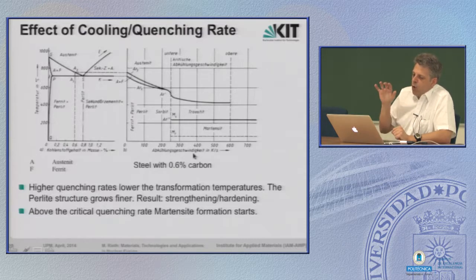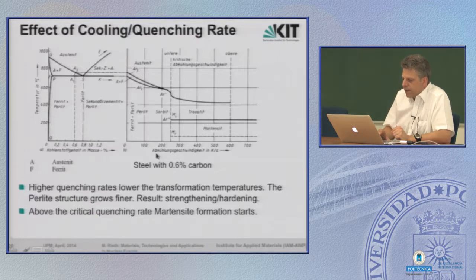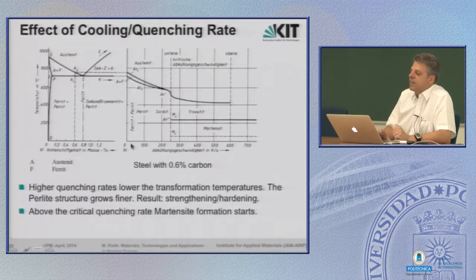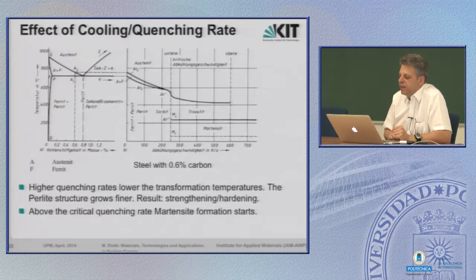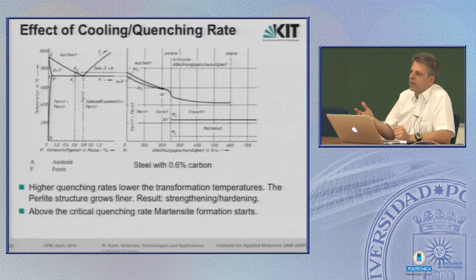Now let's see what happens if you do this more quickly. Here, again I forgot to translate, Abkühlungsgeschwindigkeit, that's the third word. That's simply cooling rate. Here we have the cooling rate in Kelvin per second. If you do it very slowly, everything happens as I have shown before, perlite formation. This is the important transition line here. If you speed it up, then as said, this line is shifted toward lower temperatures. And you can see it here in this diagram. This transformation line from austenite to ferrite and perlite, or from FCC to BCC lattice structure, goes down with increasing cooling rate. Goes down, goes down, goes down. And at that point, if we have cooling rates up to about 250 Kelvin per second, we still produce perlite in the one or other way.